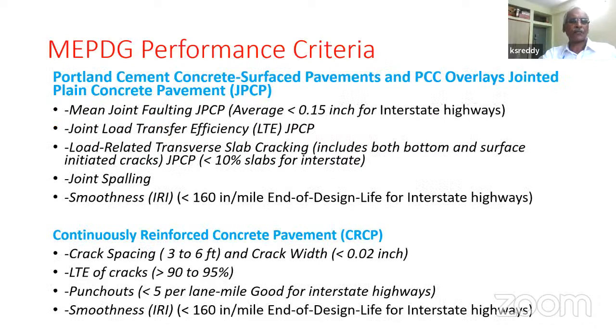Compared to this, if you look at the mechanistic empirical pavement design guide for jointed pavements as well as continuously reinforced concrete pavement, let us look at jointed pavement because this is what we normally build in India. There is joint faulting, which is a problem with concrete pavements. At the joint, both the slabs are at different elevation. So the average joint faulting should not be greater than this. For interstate highways, there is a criteria for that.